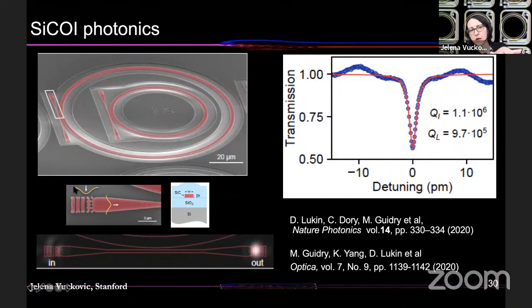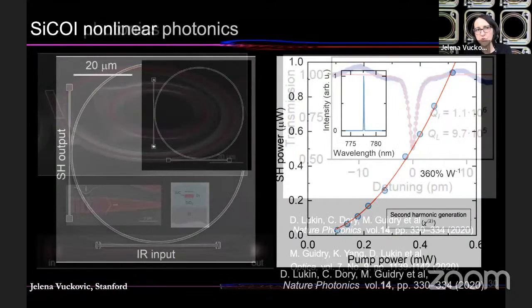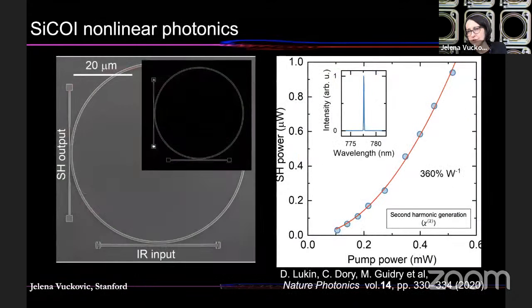And this is silicon carbide sitting on insulator, but you can also remove the insulator if you would like to have suspended structures. So once you make silicon carbide on insulator, basically fabrication is the same as dealing with silicon photonics. We've also demonstrated nonlinear optics. There is a strong second order optical nonlinearity. Initially, we demonstrated second harmonic generation with efficiency of 360% per watt, but that was at a time when Q factors of resonators were smaller by a factor of 10 or more.